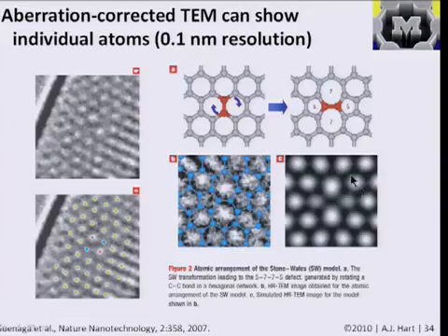And it's also more difficult to do this for atoms that have lower atomic numbers, or lower atomic weights, because an electron beam of a certain energy that may be more effective at imaging will be more likely to damage a more fragile or lower atomic weight material. So you need to have a better image at a lower accelerating voltage, for example, to image something like carbon, whereas you might be able to use a higher voltage or a higher current or a higher beam intensity to image something like zinc oxide or a metal.